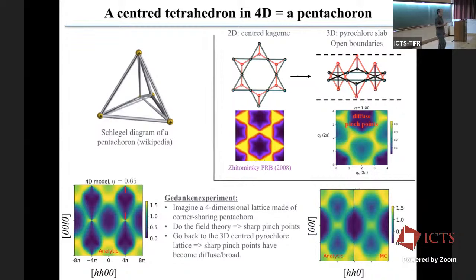Yeah. So in Monte Carlo we have checked. So this is Monte Carlo, and when you make a cut, you actually obtain exponential decay. It's exponential decay because of this. Because you have the divergence condition locally, so you have 0 magnetization on all centered tetrahedra when you make the sum of the 5 spins. But because the flux can exit through the 4th dimension, you get exponential decay.